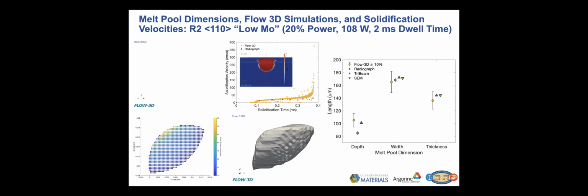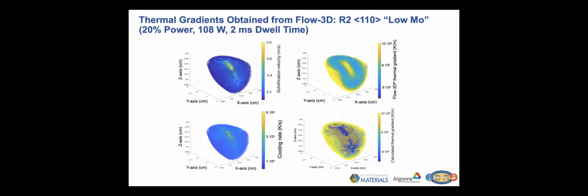And now we feel confident that, now that we have matching velocities and melt pool characteristics, we can go ahead and get the thermal gradients. So these are example thermal gradients that we've obtained from Flow 3D. So here we have solidification velocities locally in the melt pool as compared to what Flow 3D gives us. We also calculated the thermal gradients another way by using the velocity and the cooling rate experienced, and the results are shown here.